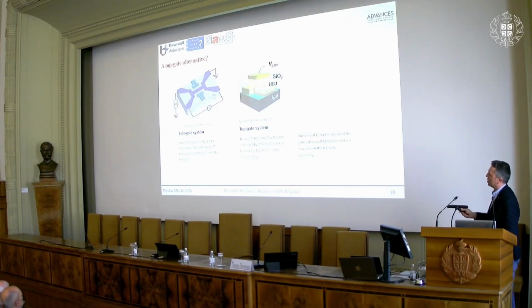So we thought this side gate system is not the optimal choice, especially not if the superconductor is thin. So we said we should look at an out-of-plane top gate system, to expose the entire stripe to the gate voltage, optimize the thickness of the oxide, which will turn out to be very important, and also optimize the width of the nanowire that is used here.